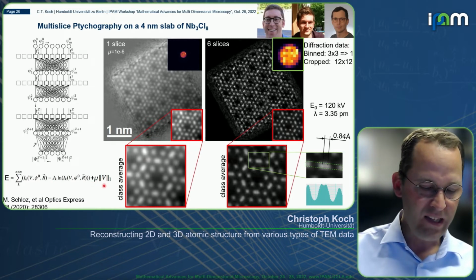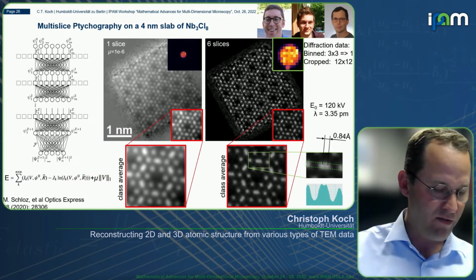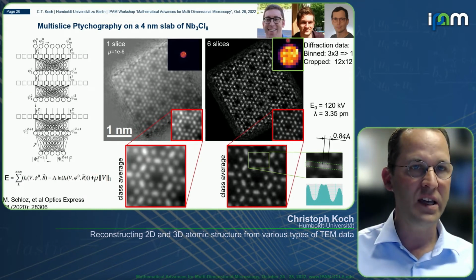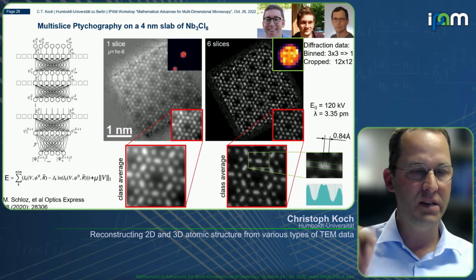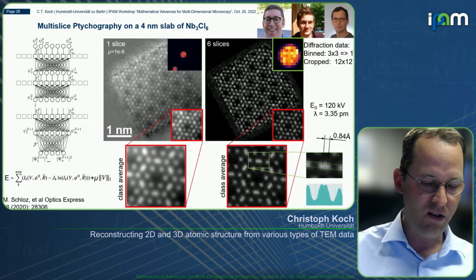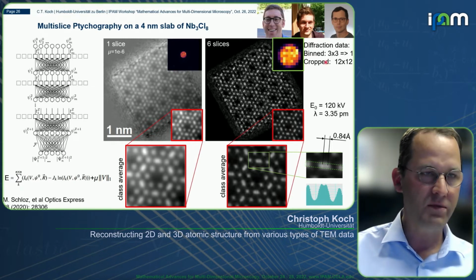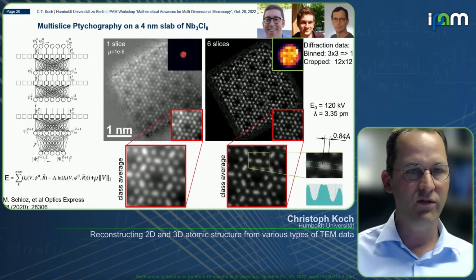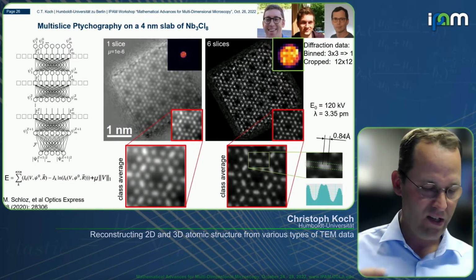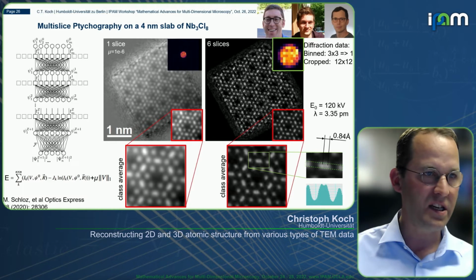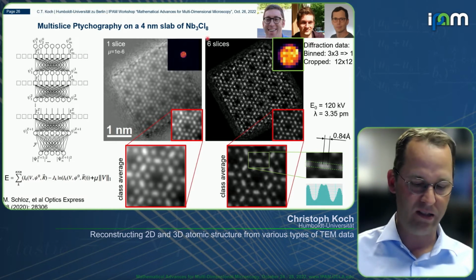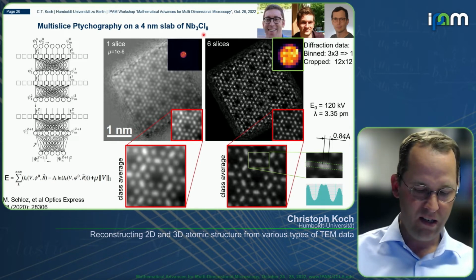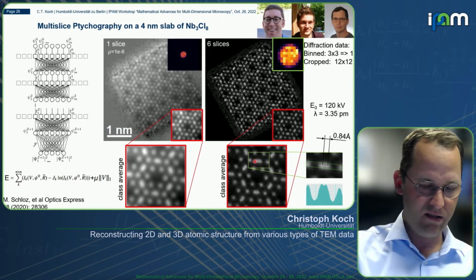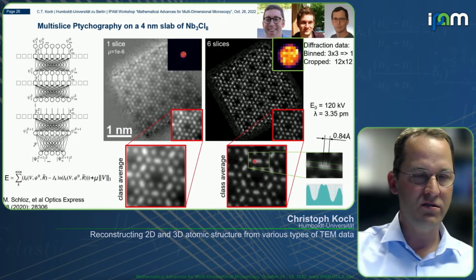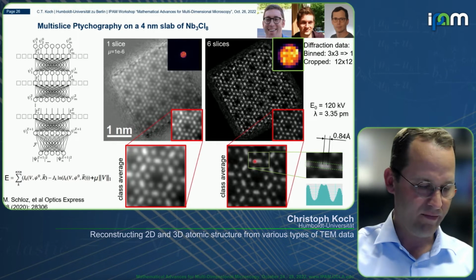and increasing this regularization parameter, the data was also reduced in size. Instead of the full data, it was binned by 3 in each dimension, and then only 12 by 12 pixels were cropped from the center of the diffraction pattern. This reduces the data set to 144 numbers per probe position, instead of the 128 by 128 pixels recorded beforehand on the EMPAD detector. And it recovered the dumbbell spacing very nicely, and also showed that the data doesn't need to be as large as one would have assumed before.